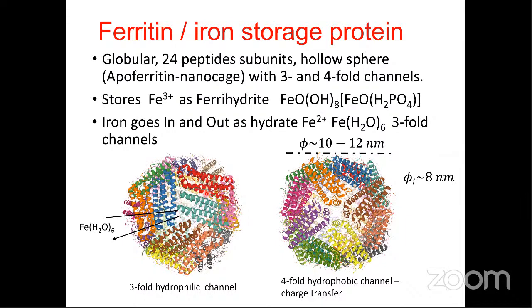So in this way, labile iron can go into ferritin and become stored there to be used when it is needed, or can get out when it is needed. The fourfold channel is hydrophobic. Being hydrophobic is not useful for this type of transfer, so it is believed it can only transfer charge to stabilize charge. And it is nice to notice that the size of apoferritin is from 10 to 12 nanometers. Let's say it's in the nanoscale also, as the particles.